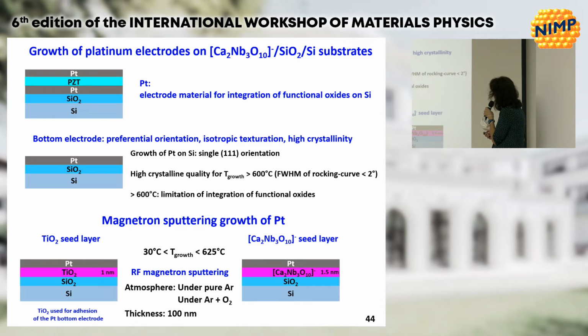So Gilles Poulain in Caen had the idea to grow platinum directly on nanosheets. It was never done before. They made two kinds of samples. The first one is silicon covered by silica, then a thin layer of titanate, which is there to increase the adhesion of platinum on the substrate. The second is the same thing, but instead of the titanate, you have the nanosheet seed layer below the platinum.